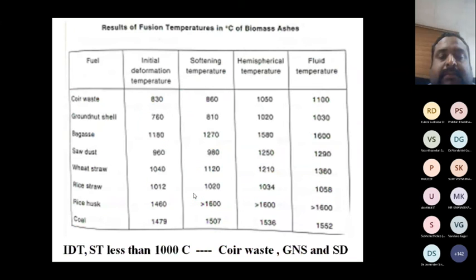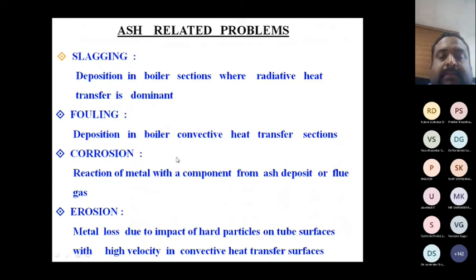So these are the results of the biomass ashes for the ash fusion temperature. You can see here coir waste, IDT and softening is less than 1000 degrees. For coir waste, 830 degrees. Groundnut shell, 760 IDT. Less than 1000 degrees. So these are the ash related problems.